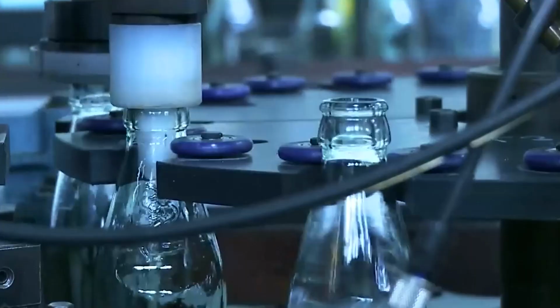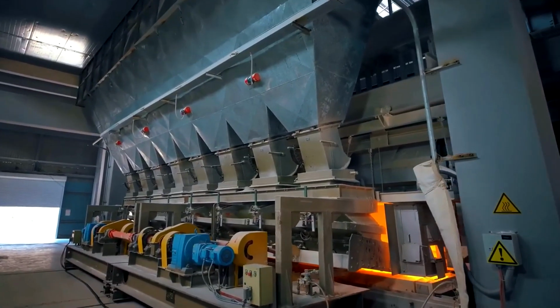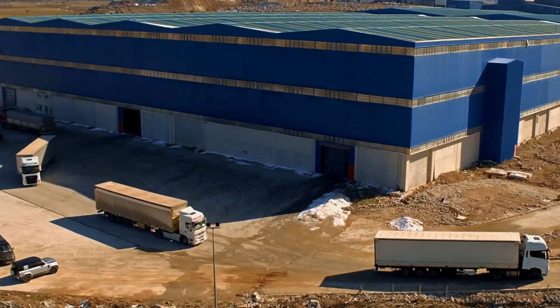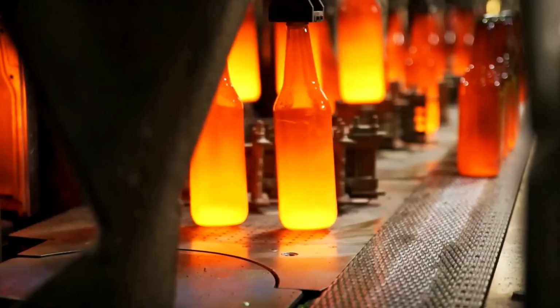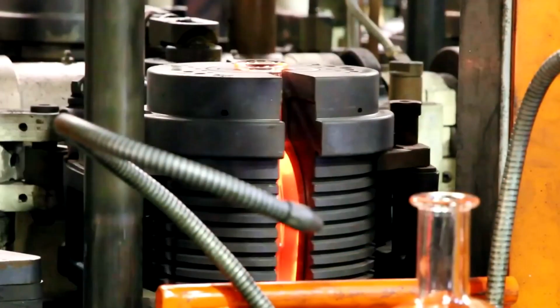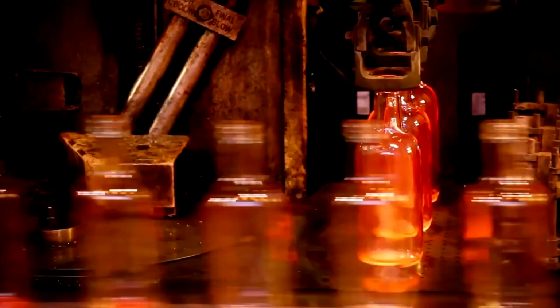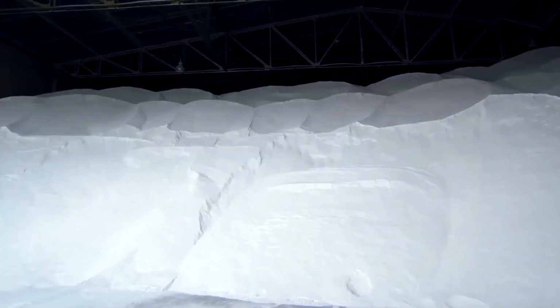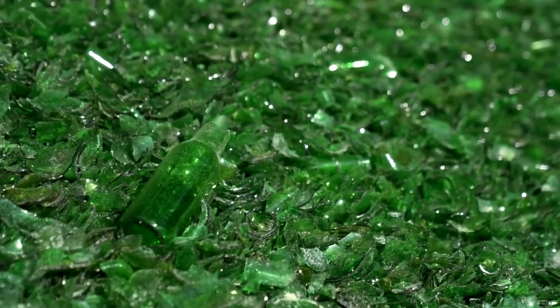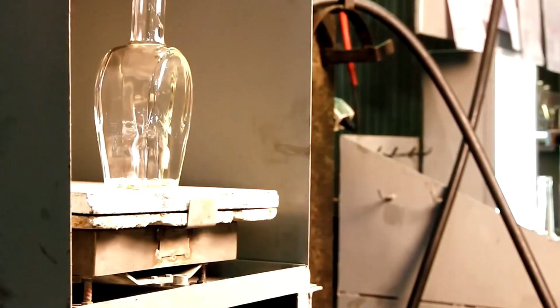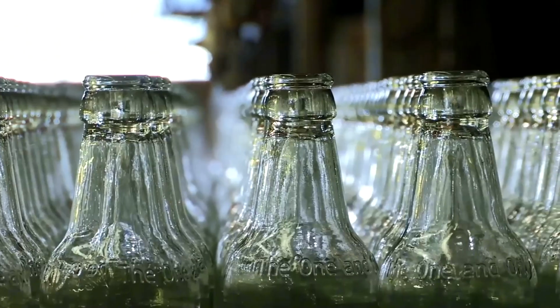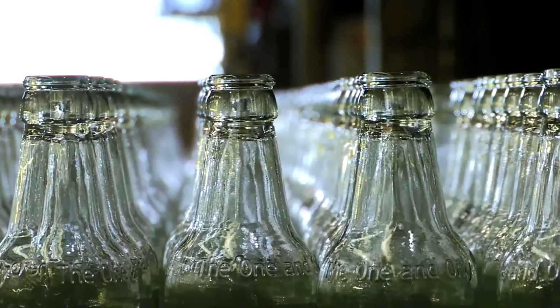70% is the maximum proportion of the batch that can be comprised of cullet, or recycled crushed glass, waiting to be transformed. This recycled material cannot enter the furnace alone after sorting and grinding, as it requires a precise blend of raw ingredients to stabilize the melt. The recipe begins with pure silica sand, which serves as the primary element bestowing clarity upon the future glass. Engineers then introduce soda ash or sodium carbonate to significantly lower the melting temperature and conserve energy throughout the entire firing cycle. Limestone is added to the composition to strengthen the final structure and ensure stability once the form hardens.